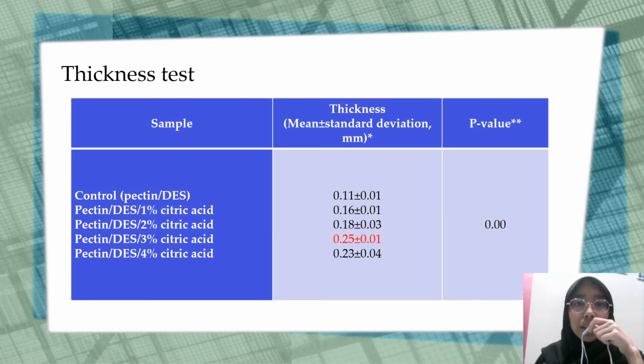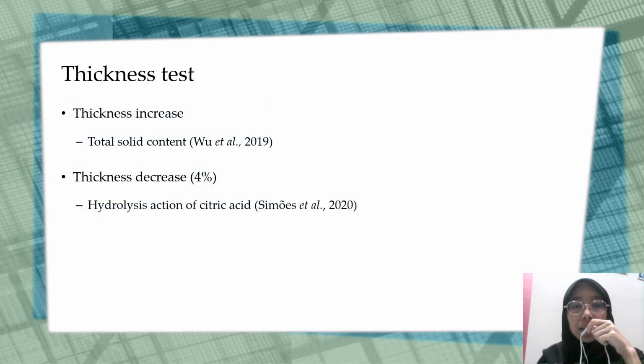3% citric acid modified pectin DES bioplastic had the highest average thickness, and the mean differences for all samples are statistically significant. Citric acid contributes to the total solid content of pectin-DES bioplastic, hence why they became thicker with increasing citric acid concentration. However, too high concentration of citric acid can cause hydrolysis of polymeric chain, which reduce viscosity and thickness of bioplastic.